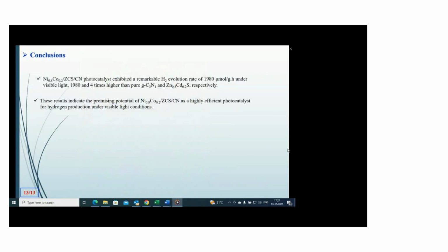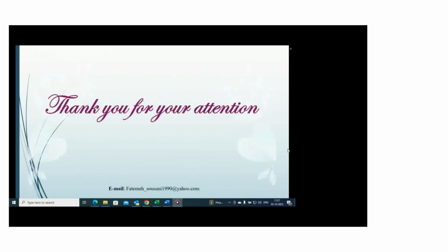In conclusion, this ternary nanophotocatalyst exhibited a high hydrogen evolution rate of 1,980 micromoles per gram per hour under visible light radiation, which is 1,980 and 4 times higher than pure g-C3N4 and ZnCdS, respectively. And the results show that this nanophotocatalyst is a highly efficient photocatalyst for hydrogen evolution under visible light radiation.